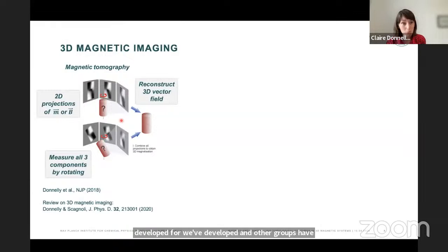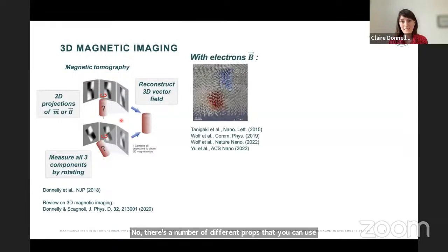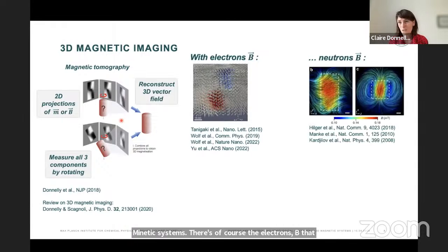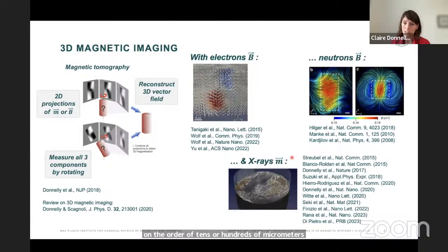Now, there are a number of different probes that you can use in order to visualize these three-dimensional magnetic systems. There's, of course, electrons, which look at the magnetic induction of your sample. Neutrons, which work on a much larger length scale, so you can look at very, very large samples up to centimeters in size, but with a little bit lower spatial resolution on the order of tens or hundreds of micrometers. And then you've also got the X-rays, with which we can probe directly the magnetization of our system.